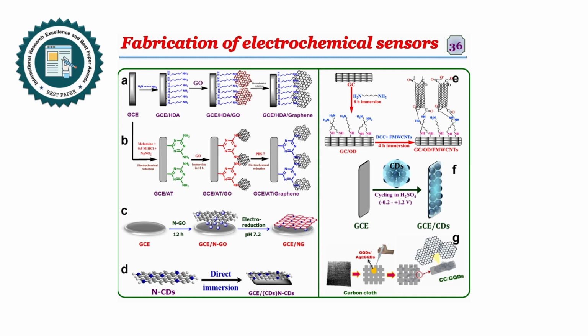Okay, the second major part of this study is the electrochemical sensing of biomolecules using carbon-based materials. For effective electrochemical sensing, we need to fabricate the synthesized carbon materials on the electrode surfaces. The first case is attachment of the carbon material using a linker. Here we take 1,6-hexadiamine. The amine terminal is attached to the carbon via Michael-like nucleophilic addition, and then the free amine is utilized for the attachment of GO, and then the electrochemical reduction leads to the formation of graphene.